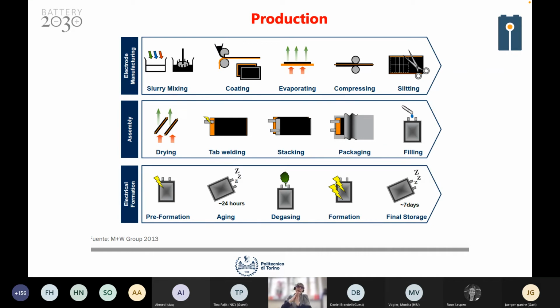Then it is compressed thanks to a calendaring system. All the exceeding parts, the metallic exceeding parts, are cut in this machine, and finally dried. Then we attach the tabs, welded on the current collectors, and then we have the stacking: one cathode, one anode, one separator, one anode, one separator, one cathode, and so on. Everything then is packed, filled with the electrolyte. And then after aging, we have the formation of the cell.